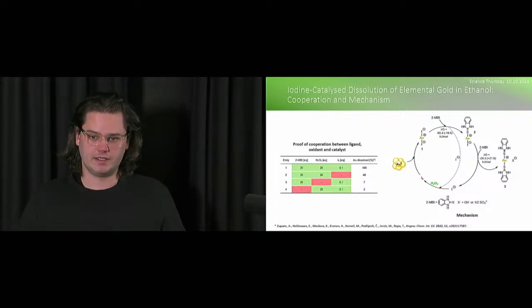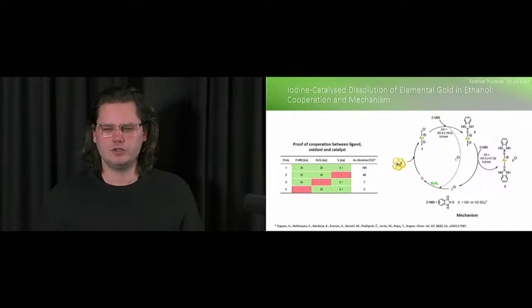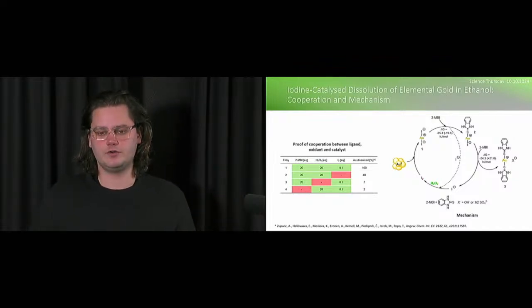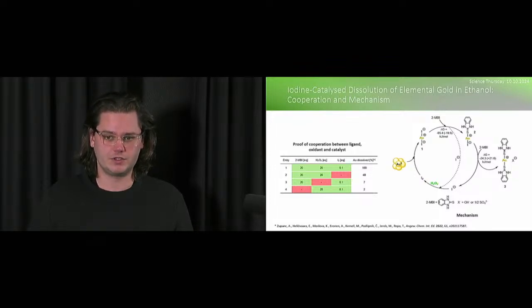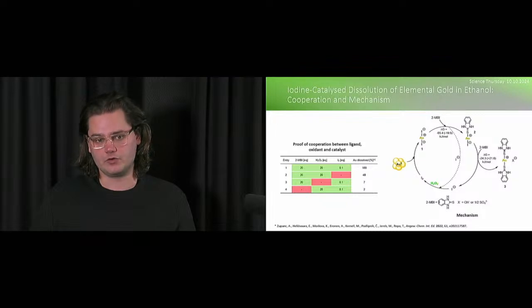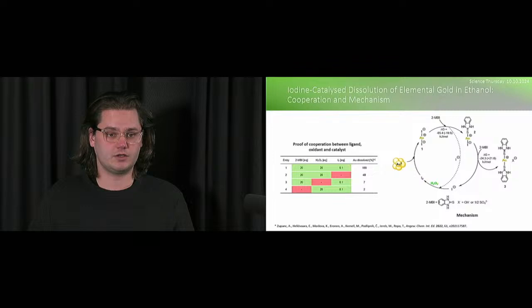If you check the table that is on the slide, you can see that if we include all, so stabilizing ligand, oxidant, and catalyst, we get 100% of the gold dissolution. But if we exclude one, we get some other percentages, and if we combine all of those percentages, we still do not come to 100. So this was one of the first proofs that cooperation between 2-mercaptobenzimidazole as a ligand, hydrogen peroxide as a terminal oxidant, and iodine as a catalyst exists.